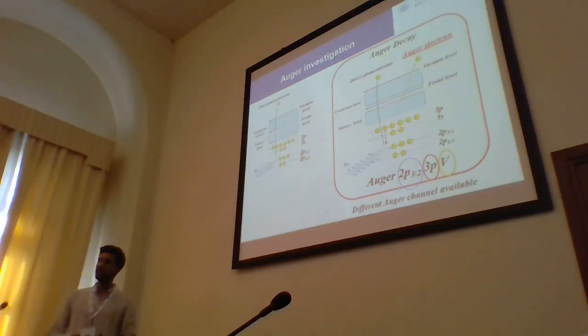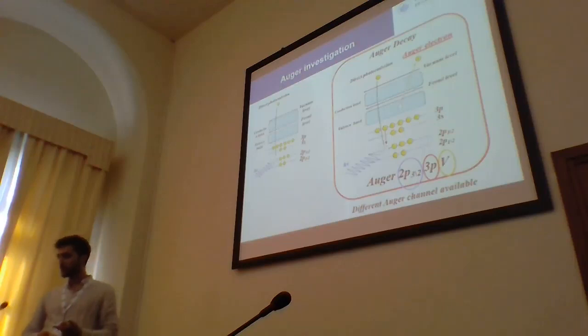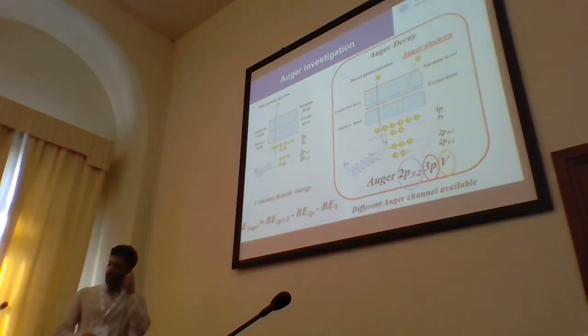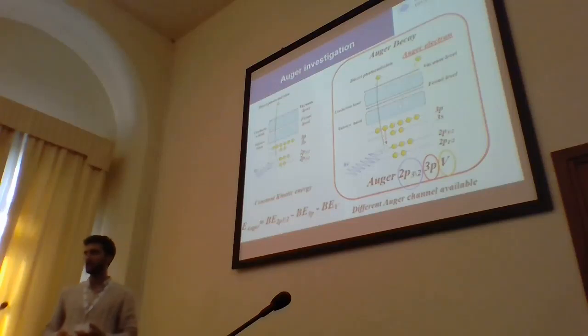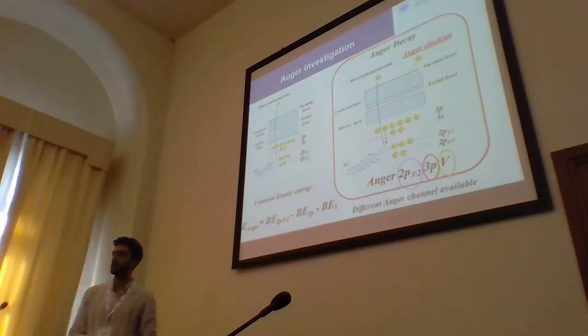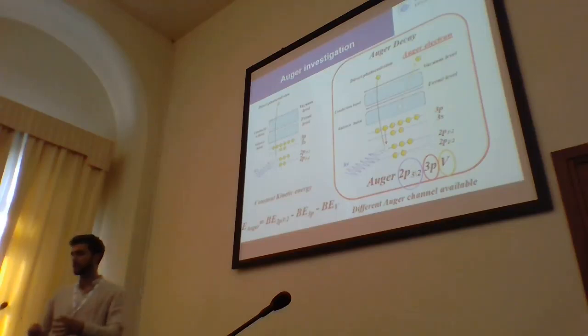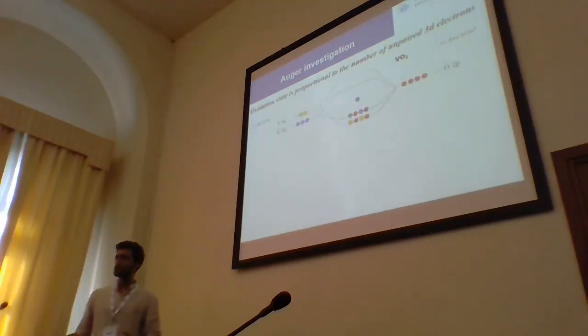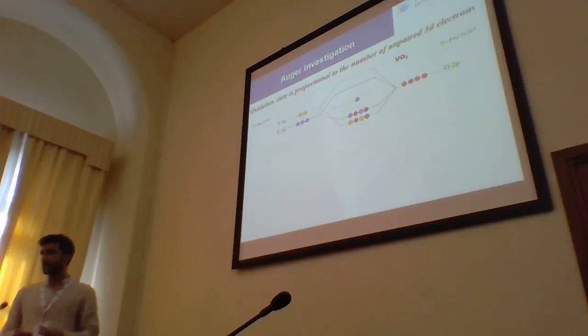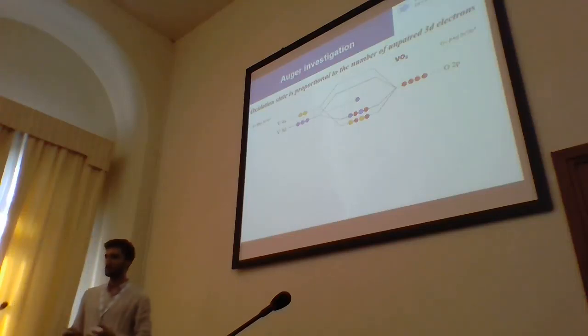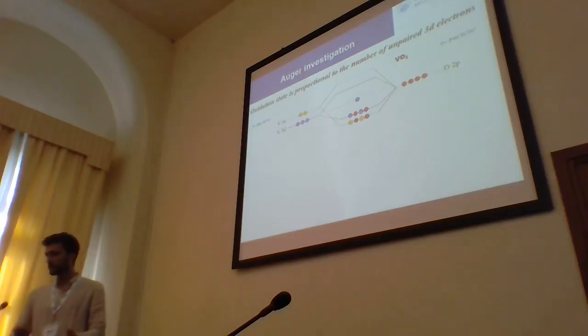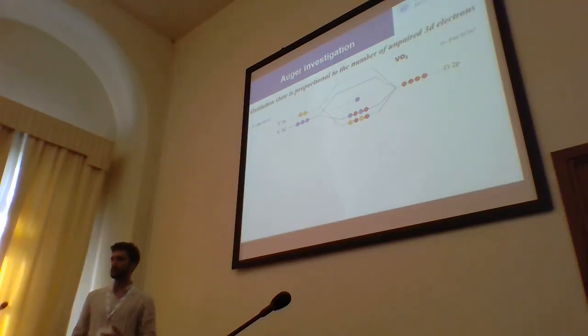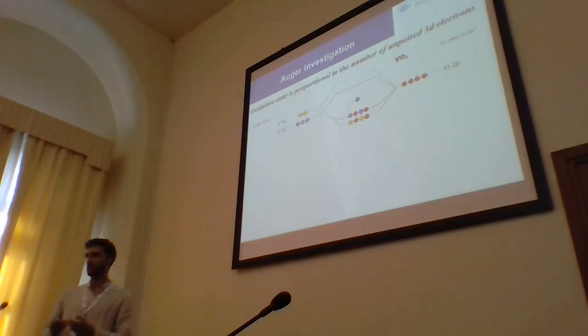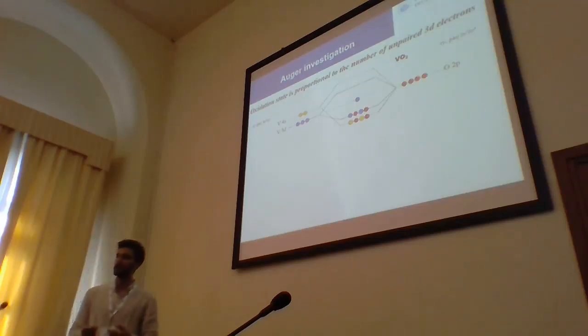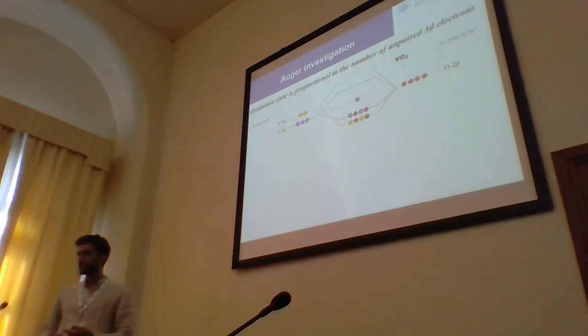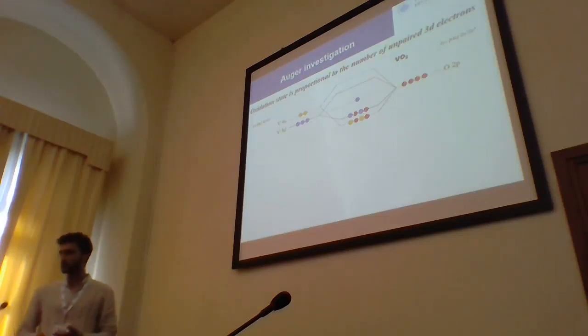With respect to direct photoemission, Auger electrons have the feature that they have a constant kinetic energy, since the kinetic energy of the Auger electron depends only on the binding energies of the electrons involved. So, oxidation state is related to the number of unpaired 3d electrons in a vanadium oxide. In this ball-and-stick graph, I depicted the electronic structure of the valence band of vanadium dioxide. We see we have one unpaired electron and some other electrons which are bound to oxygen 2p electrons.